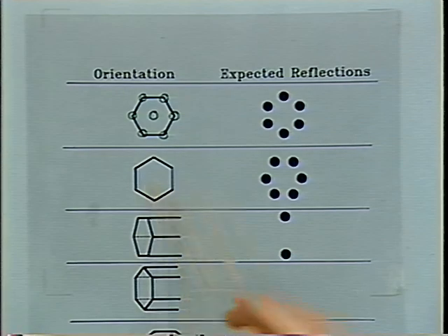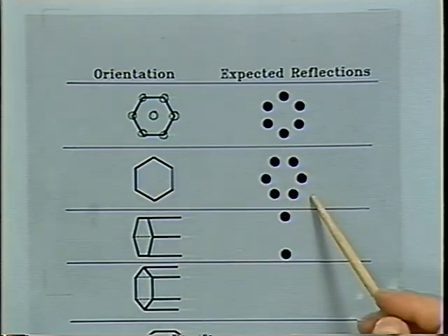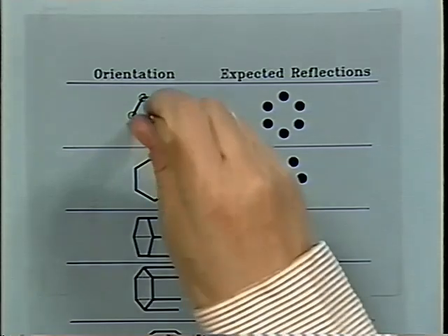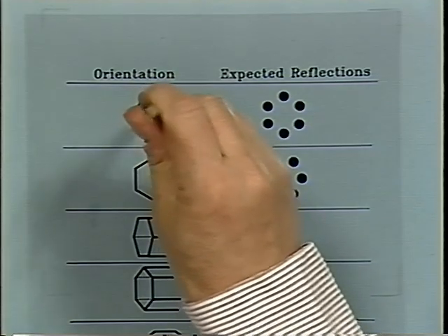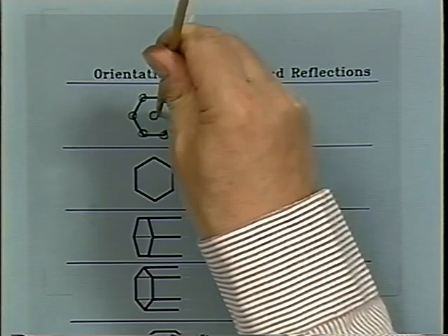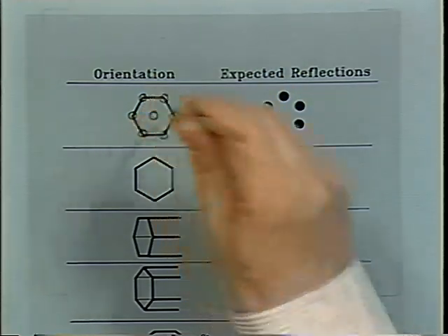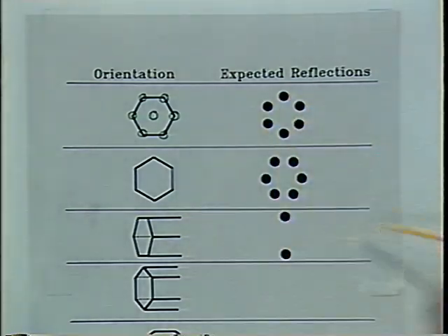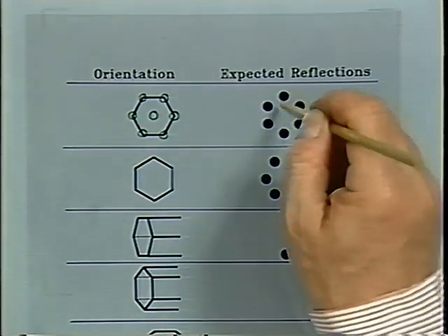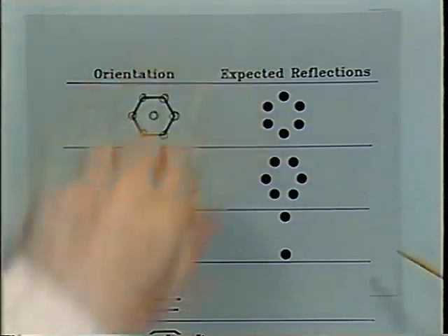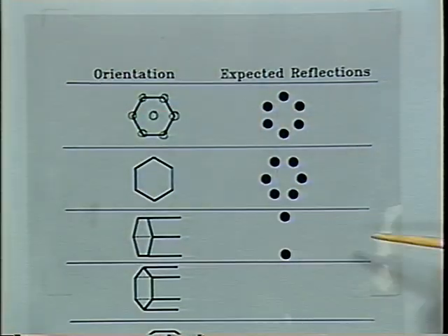If the structure is rotated, then you can see that in the X-ray again. Now, this structure has to be fairly aligned. If it's tilted too much, you won't see anything. The X-ray beam has to be along that structure. Then you see this. You will recognize the rotation of that structure by looking at the rotation of those patterns.